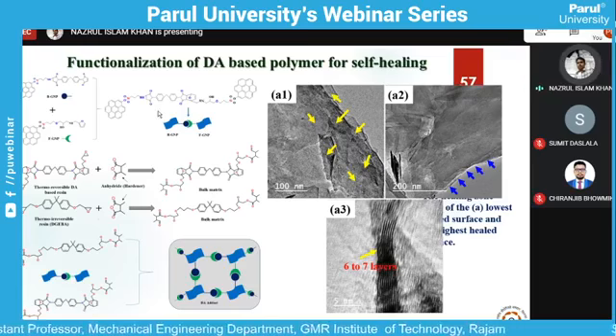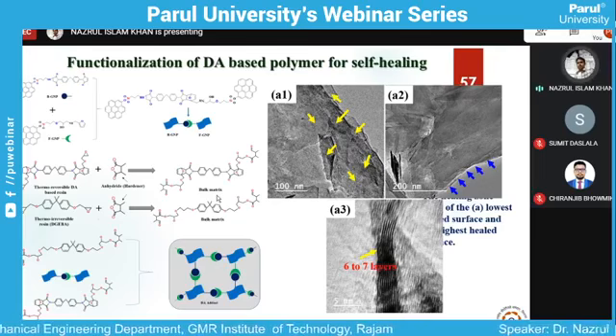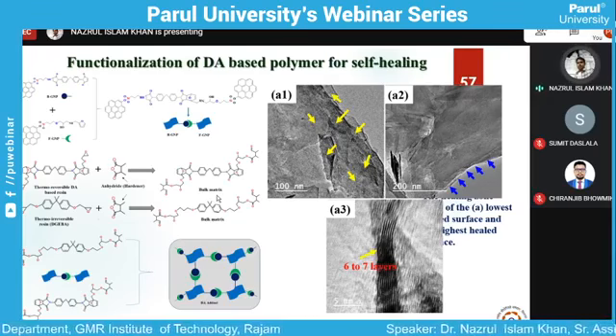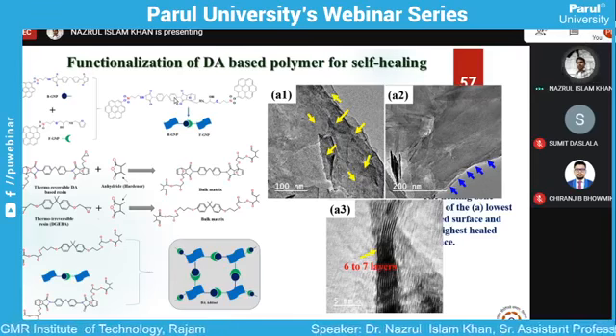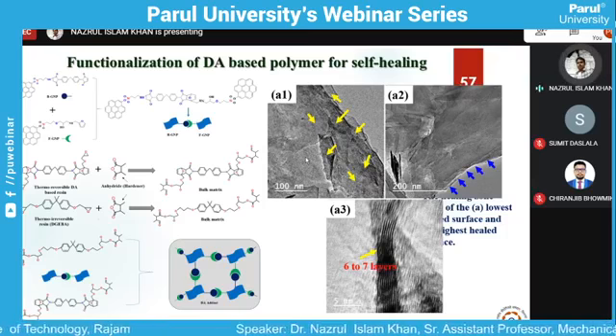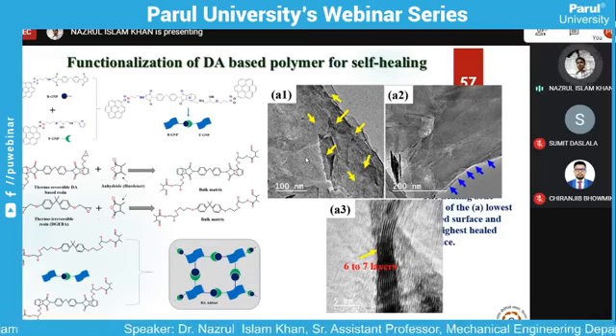If you apply mechanical force to those Diels-Alder adducts, you break that bond; just keep them nearby and apply heat, and they will again reform the bond itself without any external intervention or pressure requirement. So this bismaleimide Diels-Alder adduct, if you add it on the surface of a nanofiller, we can achieve multiple times healing capability from the polymer composite, or even apply it for CFRP composite, because our final intention was to test them in CFRP composite.